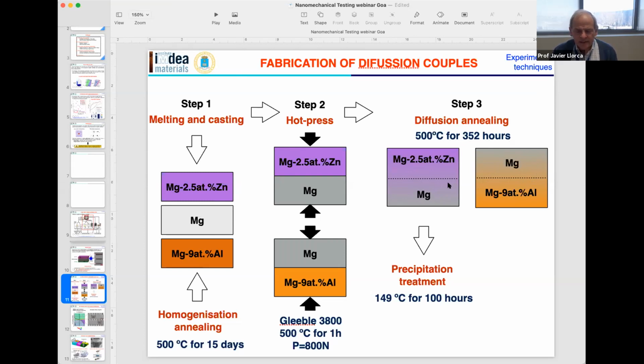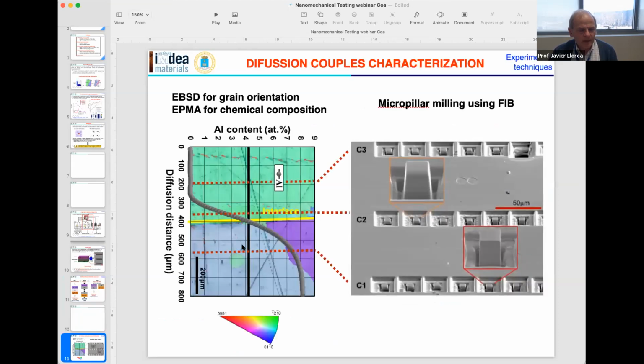Apart from that, in the case of the magnesium zinc alloy, we took samples from a region with a given composition, and we carried out the precipitation treatment at 149 degrees for 100 hours to produce precipitates within the microstructure. So just to give you an idea of what you get, this is just one example.